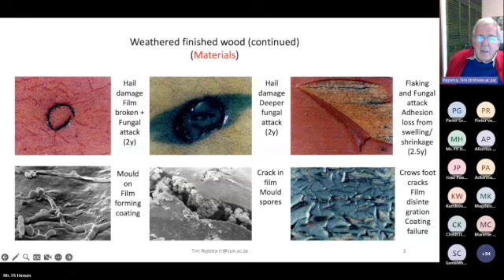And a little bit later in another coating, you can see that the elliptical pattern is actually the discoloration in the wood itself. You will notice that the wood grain doesn't show through these coating systems. They have certain pigments that will prohibit that. Then flaking and fungal attack on timber. This is a typical film forming coating that peels away or flakes away as a result of the swelling and the shrinkage that occurred in that particular part of the sample here.